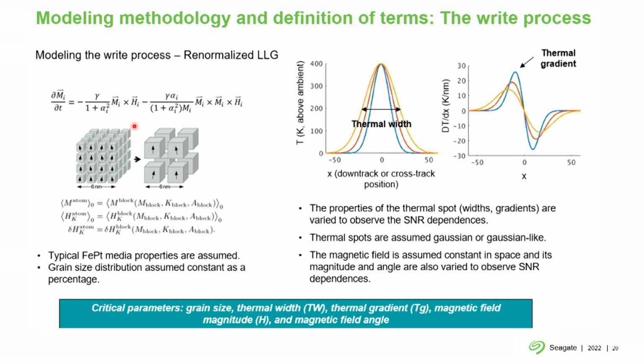So what we do is, using renormalization theory, we can estimate for any given cell size how the average magnetization of the cell will decrease as a function of the temperature. Other magnetic properties like the anisotropy and the exchange are also a function of temperature. So that allows us to use a 2 nanometer cell size as opposed to a 2 angstrom cell size.